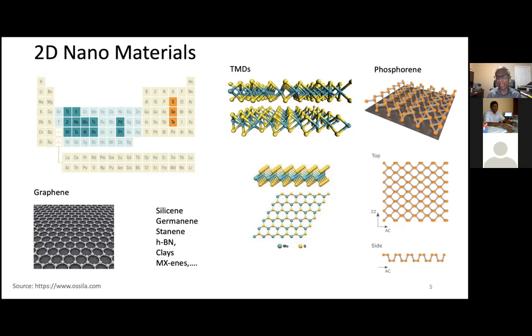They are also arranged in a layered atomic arrangement, where within the layer you have covalent bonding, but between the layers very weak van der Waals bonding. Like graphite, which is the parent material for graphene, the interlayer bonding is very weak. So it allows you to use that as a lubricant because it can shear really well between atomic layers, and you can take them apart as well.